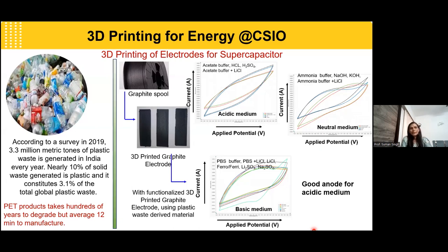With these activated carbon functionalized graphite electrodes, we studied their behavior in acidic, neutral, and basic medium, and our electrode shows the best results in the acidic medium. So to some extent, they are reflecting a battery-like behavior rather than supercapacitor. These are the initial results which we obtained. Since these electrodes showed good behavior in the acidic medium, this will be taken towards battery designs. Next, please.